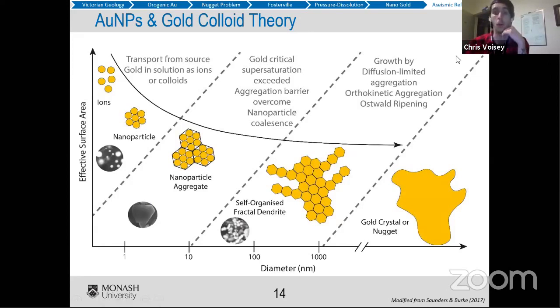The main ways that they grow are, there's diffusion limited aggregation, which is the growth of nanoparticles through some sort of either electrical or chemical gradient. You can draw them together. There's something called orthokinetic aggregation, where you physically shake them up and make them stick together. So if you have two things that are repelling, you just smack them together physically. And there's Ostwald ripening, which is particles trying to basically grow and stick together to reduce their free surface energy. Things that have a lot of free surface energy don't like it, and then they stick together. So it's the same as watching soap bubbles want to kind of merge together and grow. They're reducing their free energy. That's how they want to grow.